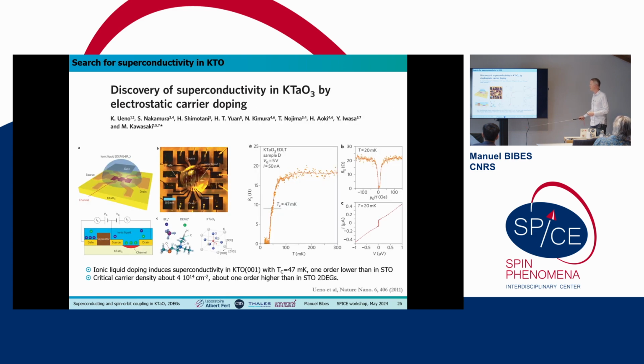And this changed actually in 2011 with a paper from a Japanese group who worked with 001 potassium tantalate, still 001, and it will become important in a minute. They were able to induce a very large charge density and to create a 2DEG. And finally, they found a very low TC superconductivity, just 47 millikelvin, with a very high charge density, 4 times 10 to the 14, which is about 1 order higher than in the case of STO 2DEGs.